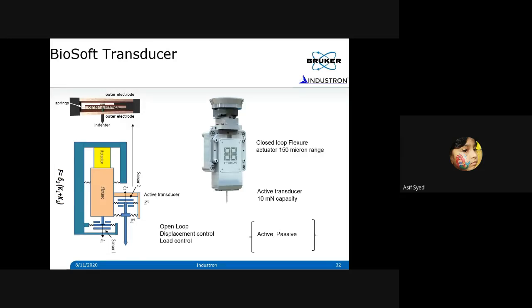That transducer is good, but when you try to understand the properties of soft materials, I mentioned that you need to have a very large throw, which means very large displacement, in hundreds of microns. That is not possible with that transducer, because the spacing between those plates is only 60 microns or less. So you can't go beyond that. Only one third of that gap is useful when you make a measurement. So we can't use the electrostatic force transducer for soft materials.